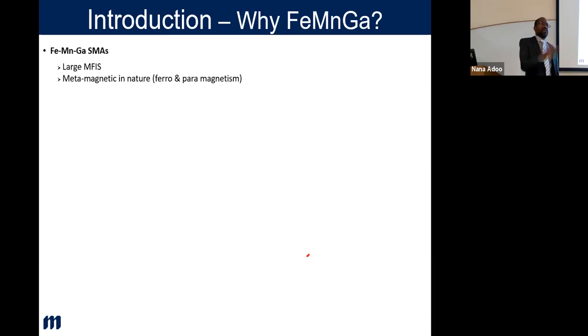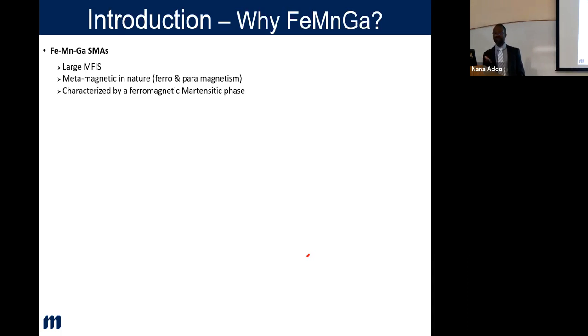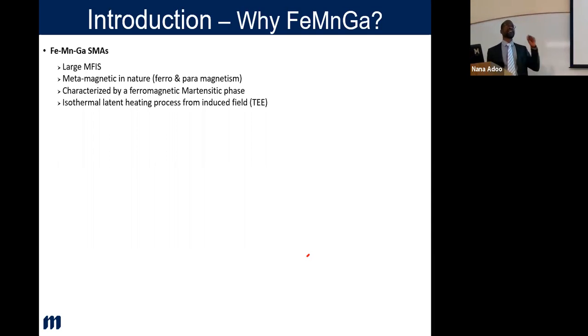At the same time, it can behave as a pure permanent magnet when you have its axis aligned with the soft axis of the field that you're inducing it with. It also demonstrates a large magnetic field induced strain, as I said previously, and it's characterized by these phase changes, switching from ferro to para, or from a para-austenite to a ferromagnetic martensitic stage. So this is all because it has that characteristic martensite in there.